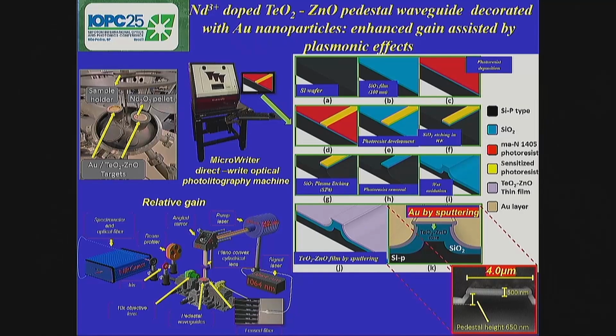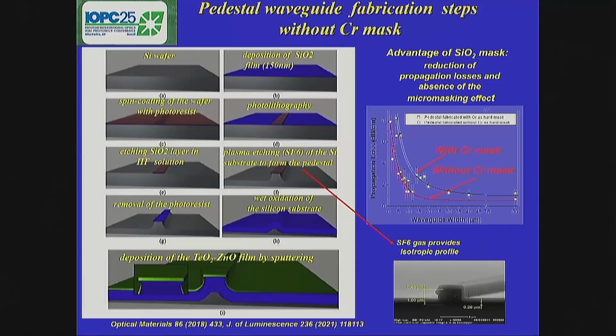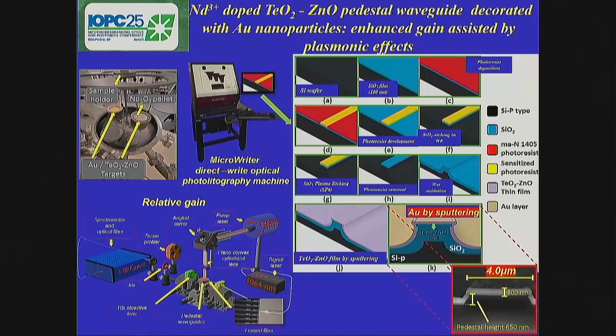Instead of using this chromium mask, we started to use a silicon dioxide mask, and we obtained two interesting things: the reduction of the propagation losses, and, as you can see in this image obtained by scanning electron microscopy, the absence of those sidewall ruggedness. More recently, we started to use a different technology. It's a microwriter with which we are able to perform direct write optical photolithography. In this case, we can draw any pattern we want. We have more flexibility.